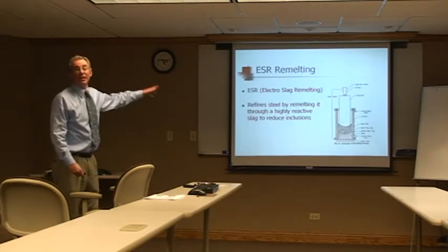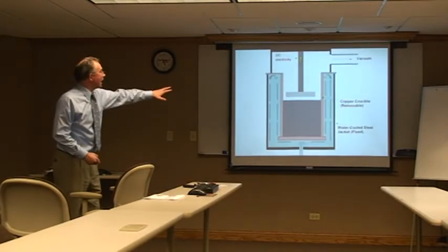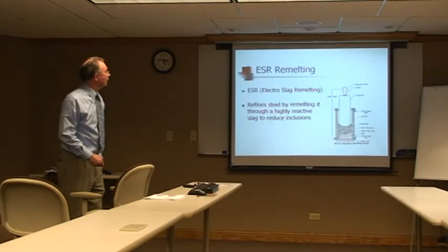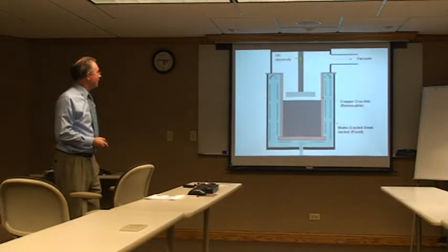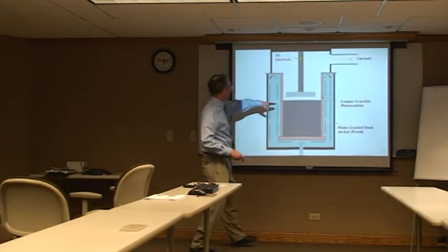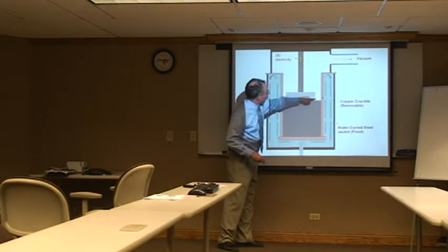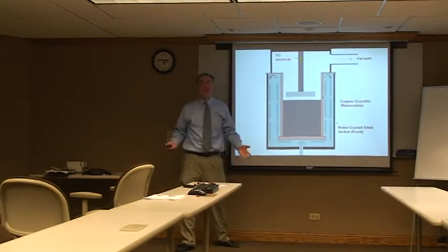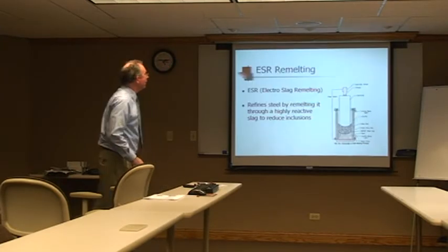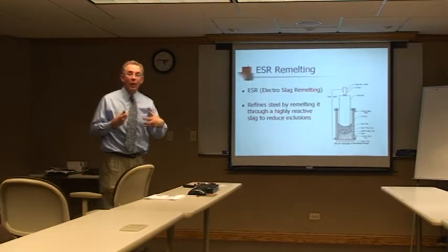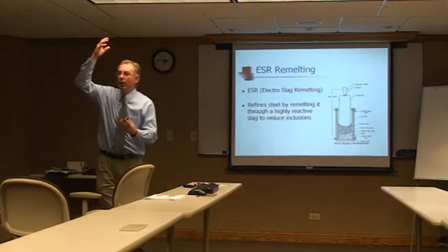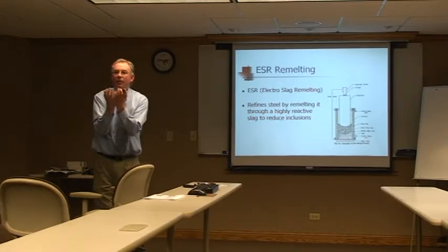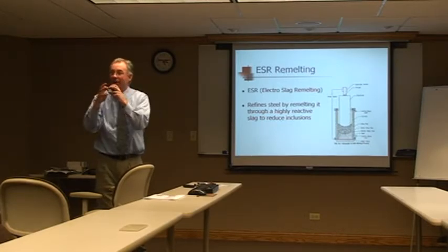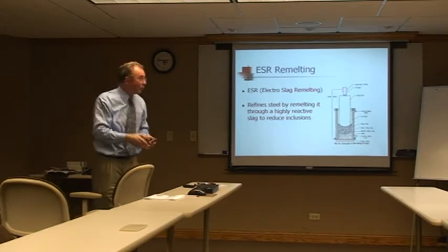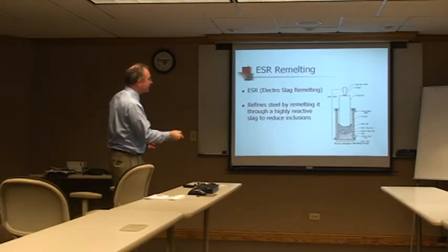Okay. ESR melting. Similar setup, except it's not in a vacuum. And the difference being, instead of this being in a vacuum, in this layer right here, we have flux, which basically is a lime flux. And there's chemical reaction going on. As the steel goes through that, any inclusions chemically react with that flux and are absorbed into the flux, and the liquid steel passes through the flux into the solidifying ingot below.